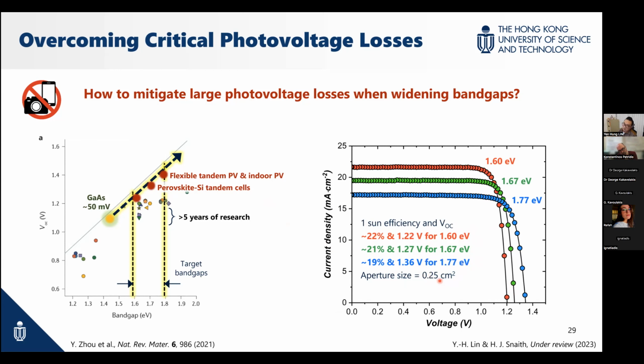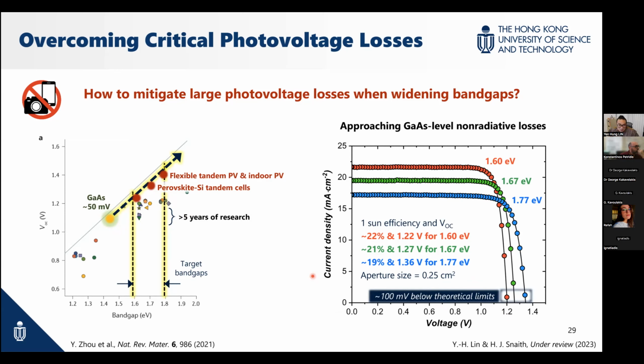Something a little bit different here is we didn't make small pixels. We make pixels at least 0.25 square centimeter or 1 square centimeter. For 1 square centimeter, we achieve a similar level of enhancement. To put this into perspective, relative to the detailed balance theoretical limit, we are only 100 millivolts below the limit. So essentially, we are extending what can be achieved in gallium arsenide to perovskite solar cells, just under exactly the same molecular treatment. A lot of passivation molecules won't be able to apply to different compositions. But here, with this kind of treatment, we are able to do so.